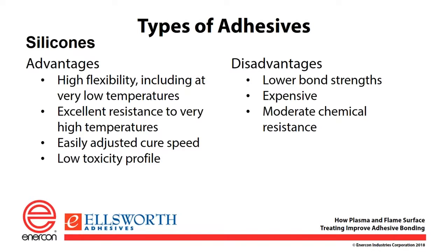Silicones are not structural adhesives, but they still get used where adhesion is necessary. They have advantages. They're highly flexible, including at very low temperatures, so they are good materials when working with CTE mismatches. They have excellent resistance to very high temperatures, so they are kind of a go-to material when very high temperatures are required but super high bond strengths aren't required. They're easily adjusted in terms of cure speed, and another big advantage is they have a very low toxicity profile. The disadvantages: they do not provide the kinds of bond strength structural adhesives provide. They tend to be expensive, and they only provide moderate chemical resistance.